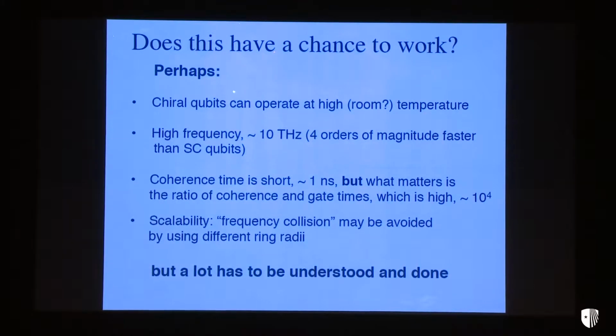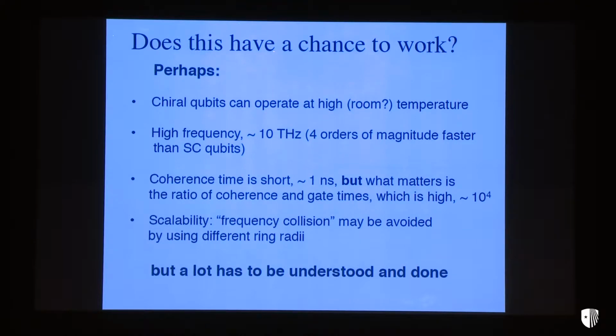The answer at this point is not known, but I think it's quite possible because these qubits can operate at high temperature. We saw that this measurement with the control of these currents was done at room temperature. These currents can be controlled at high frequency of about 10 terahertz, which is 4 orders of magnitude faster than you can control current in superconducting qubits. Coherence time is short, but again, the gate time is much shorter. So the ratio of coherence time to gate time can reach about 10 to the 4th, at which the quantum error correction algorithms about which you heard will work.